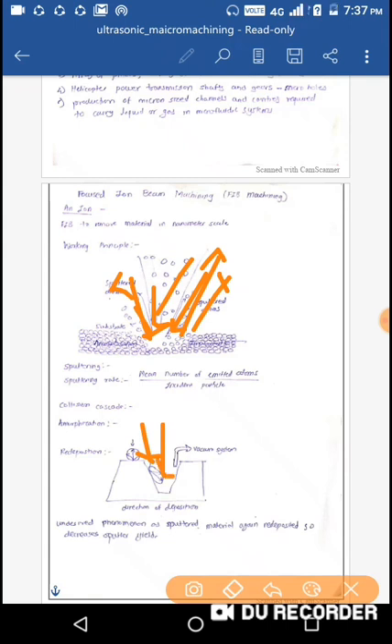So actually where the hole is made, the atoms which are not able to evacuate go inside the narrow slots or narrow holes, and these are nothing but redeposition of atoms, and they are difficult to evacuate from the bottom surface. So this undesired effect causes degradation of the quality of the milling operation. This phenomenon can be reduced by maintaining the beam current, dwell time and beam spot overlap percentage.